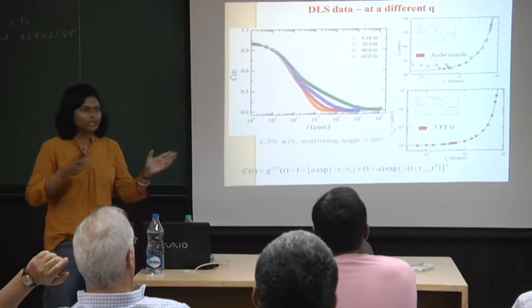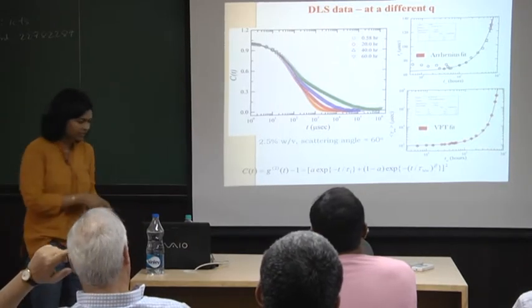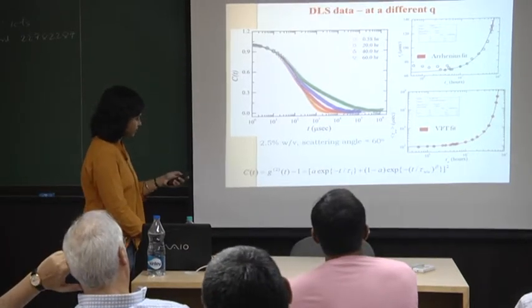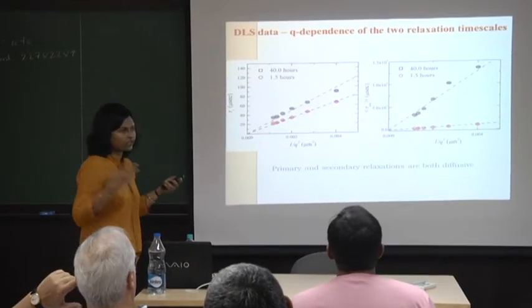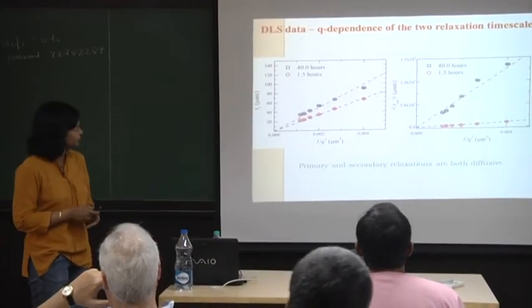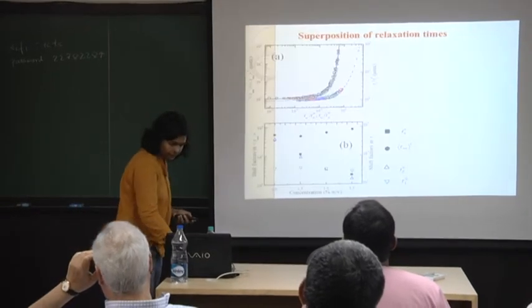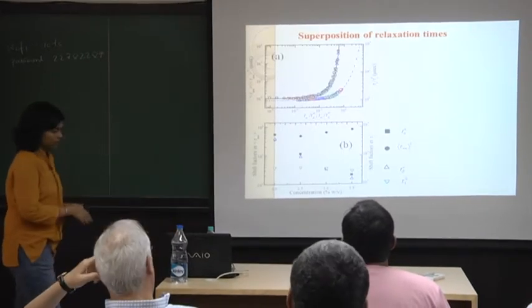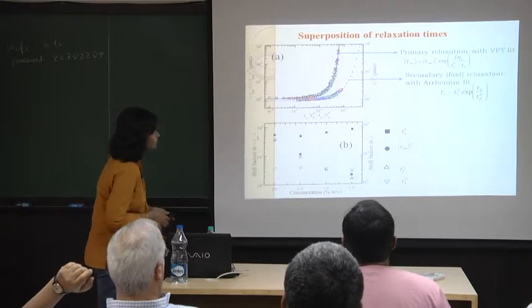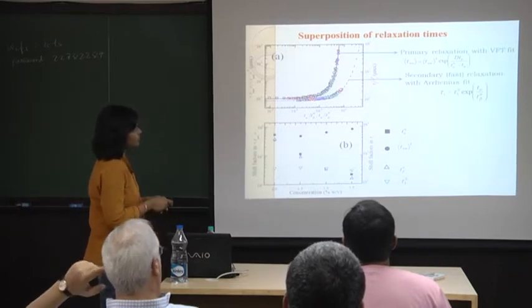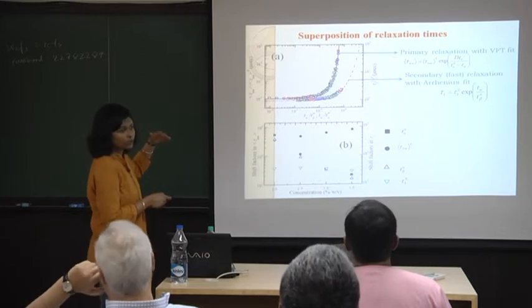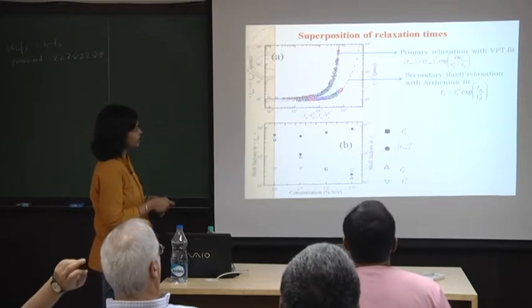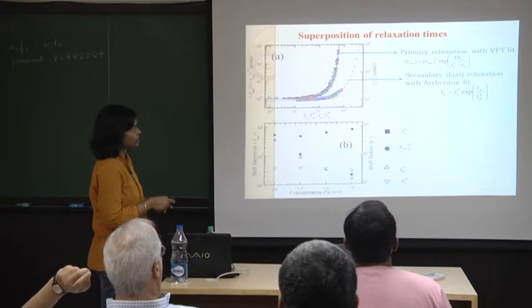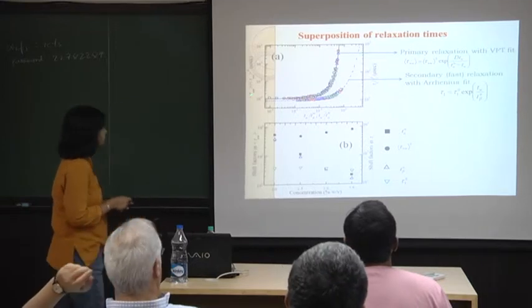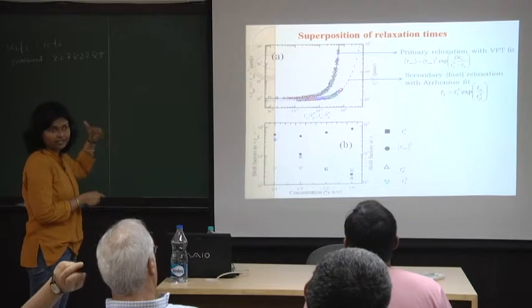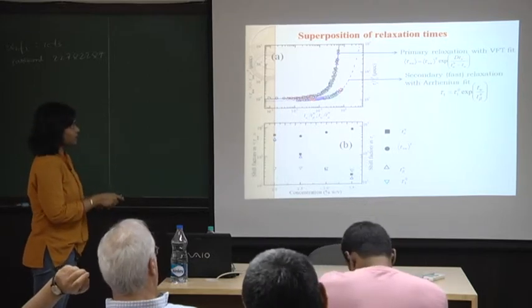If you're wondering what happens at different Qs, at different angles, the same thing happens. You get similar fits. And if you're wondering what the two relaxation times are like, they are diffusive. You can superpose the data. You'll remember that the fitting forms look something like this. Here this is the relaxation time when you've just made your sample, very fresh samples. This is what we're going to now start calling the Vogel time. This is the fragility parameter. So you just normalize the relaxation times that you've estimated by this number.